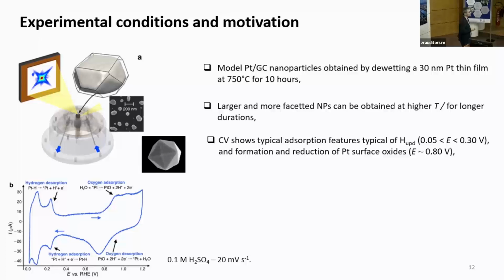Yeah, I see the point. If the equilibrium shape will change as a function of the electrode potential. Clément can probably answer better, but we didn't see any change in morphology. I think this is due to the fact that, as you say, these particles are very large. They are 300 nanometers, so there are a lot of atoms to move to see any change in the equilibrium shape. Maybe this is true for small nanoparticles.